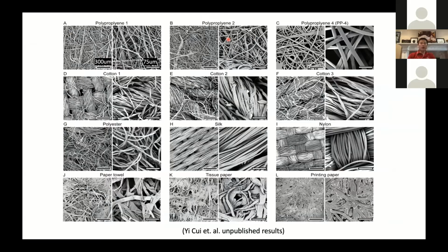If you look at the fiber diameter right there, these are the scale bars, the left side 300 micron, right side 75, more zoomed in. They're about 1 to 10 micron in diameter. They all have this porosity, somewhere about 10 to 30 microns also. But polypropylene 1 has very high filtration efficiency. It's about 95, 96%. Polypropylene 2, you go back and take a look at this. Polypropylene 2 dropped to 33%, much lower.